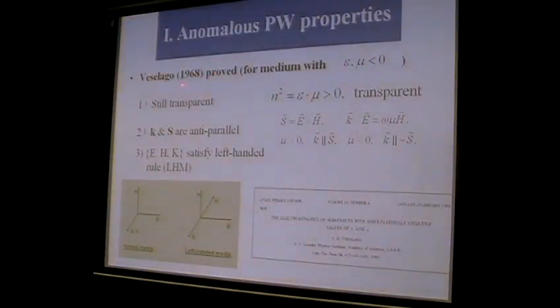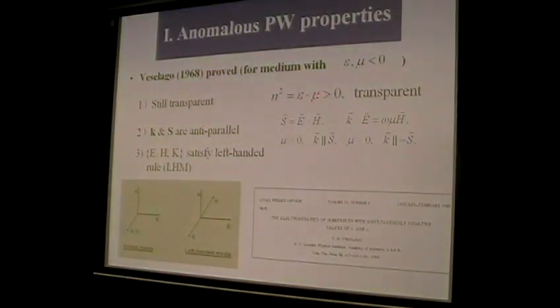Over 40 years ago, a Russian scientist proved that for a medium with both negative epsilon and mu, if you look at the dispersion relation, the refractive index is still real, because n squared is equal to epsilon times mu, and if both epsilon and mu are negative, the product is still positive, so the system is still transparent. However, if you look at the Poynting vector, you'll find that here the Poynting vector is antiparallel to the phase vector, and it's very easy to prove.